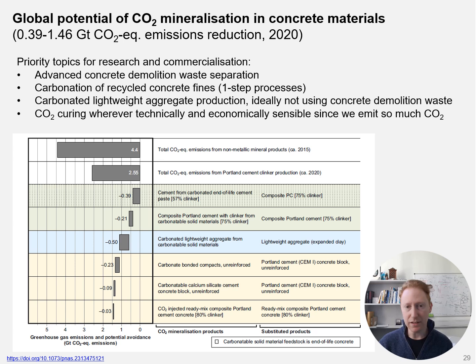The study then considered applying the most promising CO2 mineralization technologies simultaneously and calculated the potential CO2 emissions reduction, which ranged from 0.39 gigatons in 2020 for carbonated recycled concrete fines only, up to 1.46 gigatons of CO2 equivalent emissions reduction for all the technologies you see shown on this waterfall plot below. And they are carbonated recycled concrete fines, carbonated lightweight aggregate, and CO2 curing of concrete products.